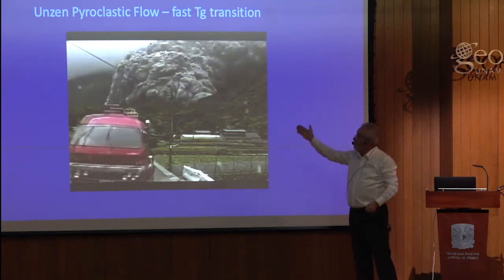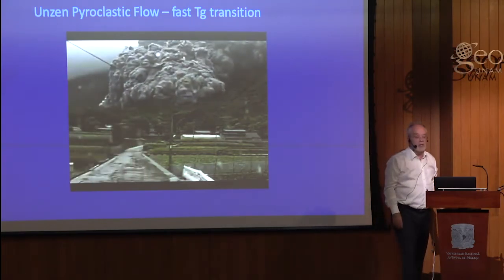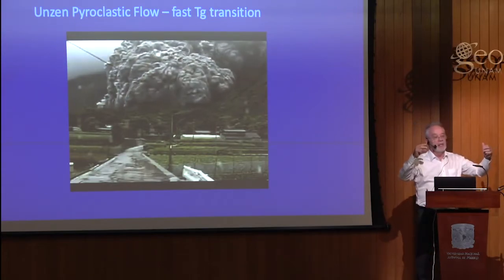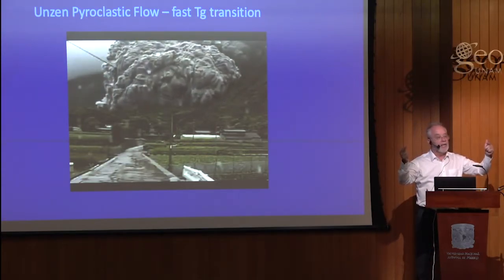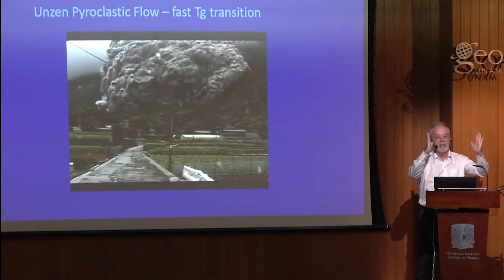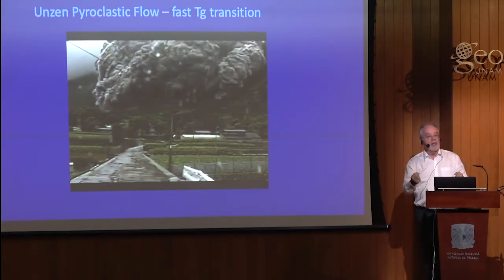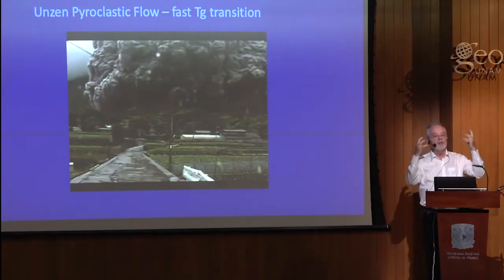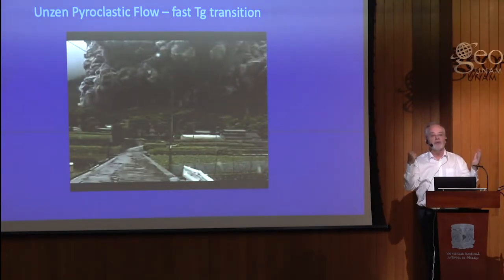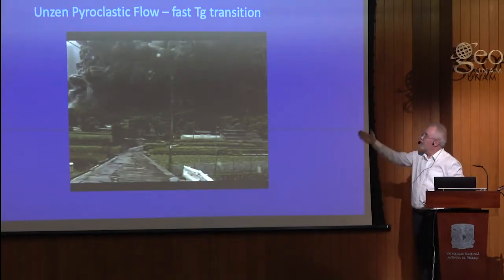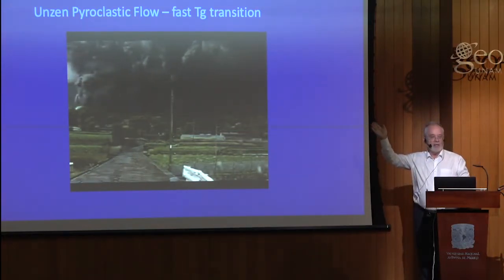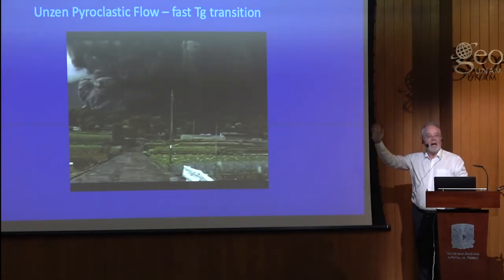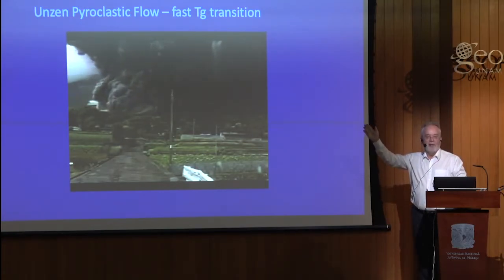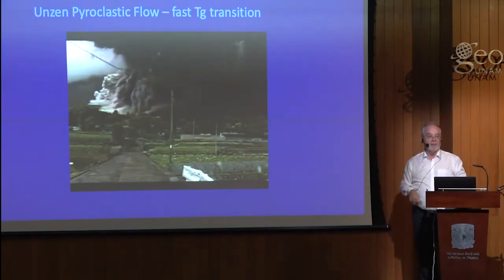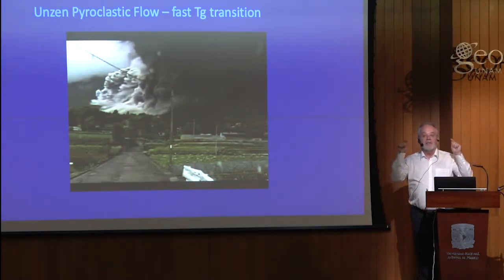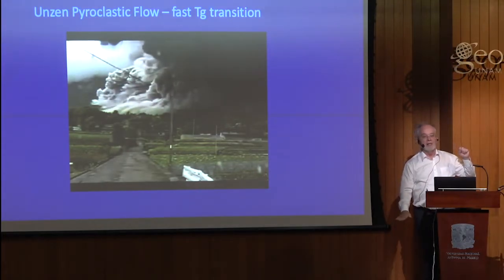And what happens in the case of a collapse of this system is the slowly flowing viscous mass fails due to some surface-related structural criterion, perhaps just over-steepening, and as a result, it fragments. And the overpressure in the bubbles of the rock contribute to the energy. Once you give them a little bit of a push over the edge of the strength of the rock, the entire rock disintegrates into massive clouds of dust. And this is the same kind of transition into dust, into ash, which you see in Plinian eruptions. It's just much more difficult to see because in Plinian eruptions it's happening underneath the surface of the vent.